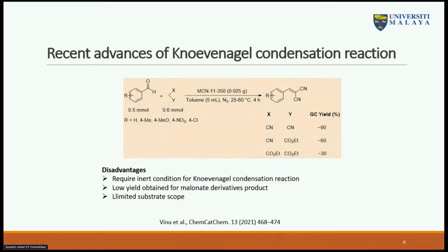carbon nitride, and the work is showing a very good GC, or gas chromatographic, yield, which indicated that when using this kind of active methylene compound, it gave very high yield, around 90%. However, when this reaction was conducted using this kind of active methylene compound, it's only producing around 30% of yield.